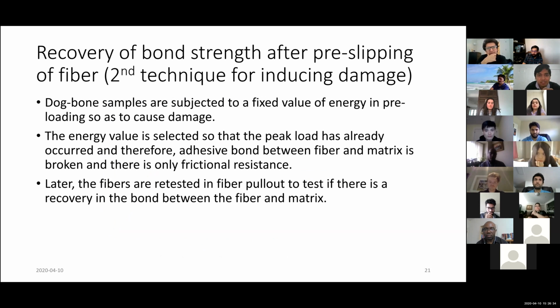So that was one technique of inducing damage, which is through a constant flow of air in the early age. And this is the second technique that I use for inducing damage to the samples. In this, I use the dog bone samples and loaded them up till a certain value of area under the curve.